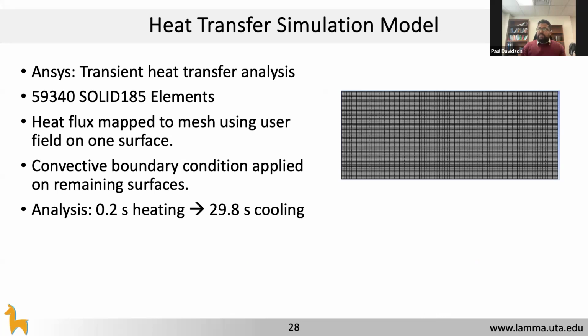So we ran a heat transfer simulation model, which is a fairly straightforward model using transient heat analysis in ANSYS. Essentially we replicate the plate and then apply all the boundary conditions. Specifically, the boundary conditions on the flux we take from our radial basis function interpolation, right? And then we ran a two-step analysis. One is heating of 0.2 seconds, then cooling of about 30 seconds.